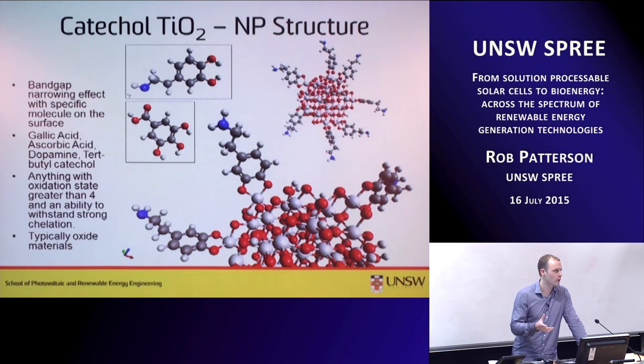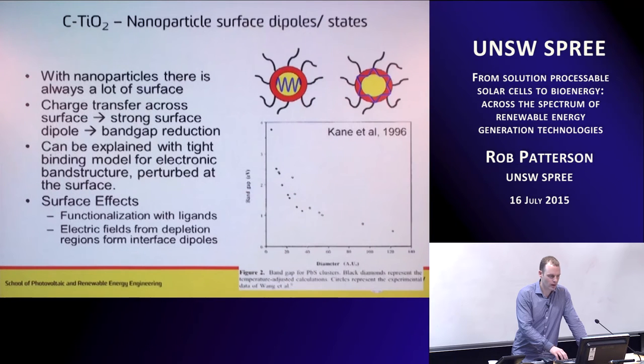And I was curious to see if I could reproduce this with some modeling. So I did a little bit of that. But I just wanted to say before I show you the modeling that this is kind of a general problem. If you have strong surface dipoles in your material, then you can end up with saturation of your bandgap as you go to small sizes. And this has been shown. Kane showed this in 1996.